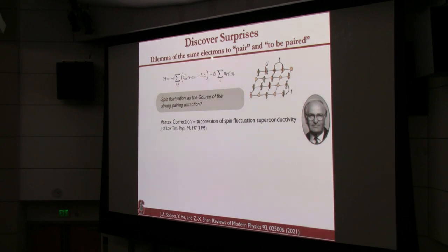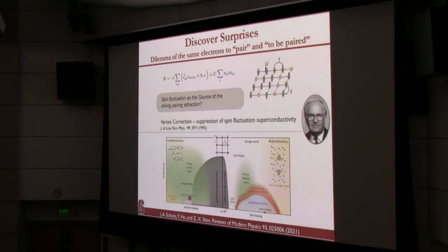He basically said, if you do the spin fluctuation theory, you need to take into account this effect of impact on the electron itself. And he pushed in one particular limit, the long wavelength limit, and showed this exactly canceled out. That's the vertex correction. And these problems are very difficult to test directly in experiment. So recently, I think, the so-called electron-doped cuprates allow us to make a test of that.